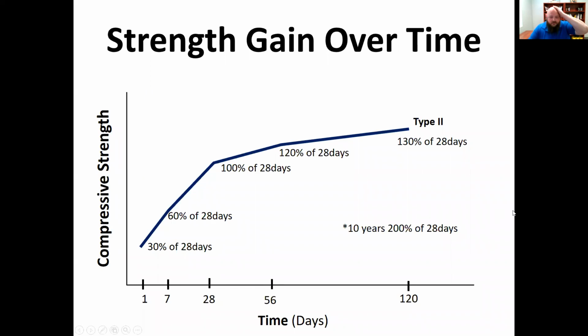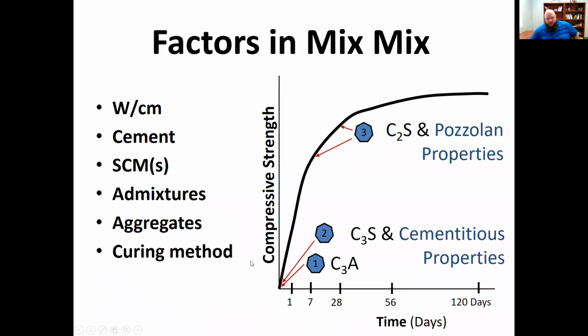And again, like I showed you before, this is kind of a strength gain over time. So, just kind of be ready and understand, are you looking for early age strengths or later age strengths? And what you do if you didn't meet your mix is change the water cement, change the sand, change the SCMs, the admixture, the aggregate, the curing method. Lots of things will play into this mix.